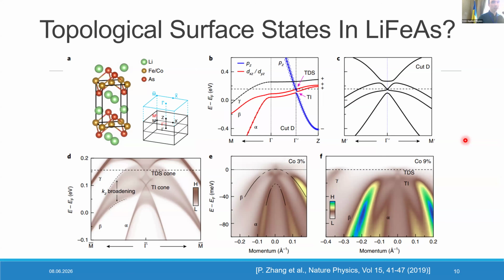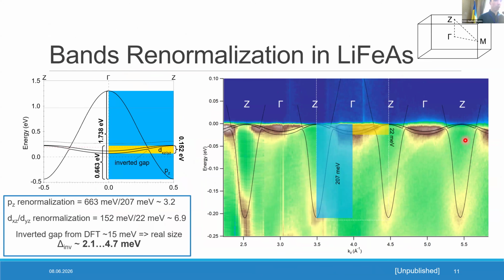So again, same as with iron tellurium selenide, there were some studies which were showing topological surface states. At the same time, in pristine LiFeAs, STM showed that there are no MZM in it, so there are no topological surface states. And why is that? We tried to figure it out, and we started from a careful study and comparison of, again, synchrotron ARPES to the DFT calculations. And first of all, we wanted to figure out what the renormalization is, what the scale of these important factors is which shape the inverted gap and from where the surface states should arise.